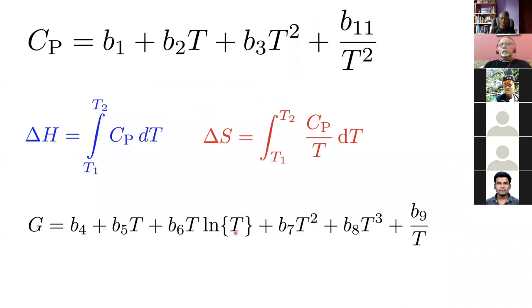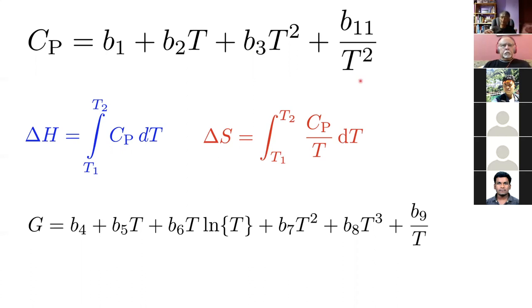The fundamental property we need by measurement is the heat capacity. In these generalized models of solutions we express the heat capacity as an empirical polynomial. This particular polynomial is found to work extremely well in representing measured heat capacity data. If it doesn't work well over the entire temperature range, that's not a problem — in a computer you can stitch it with another such equation working in a different domain of temperature. You represent heat capacity empirically because it varies in a complicated way with temperature.